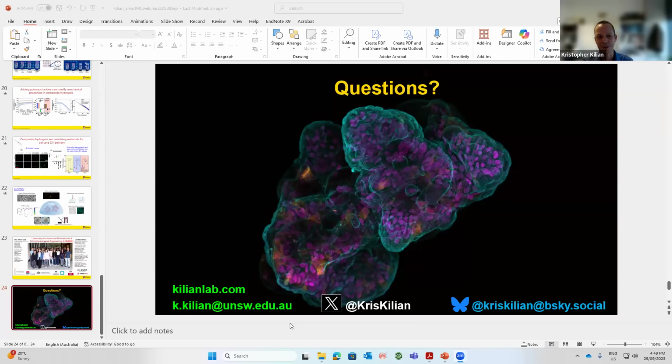And so we had to form the composite gels first and then seed the cells. And so we did an early two-dimensional characterization. But we've since moved on to more gentle chemistries. And so we're exploring the polyethylene glycols with the maleimides, where we have the dicysteine terminated peptide for the click, quote unquote, and they're perfectly viable and happy there.